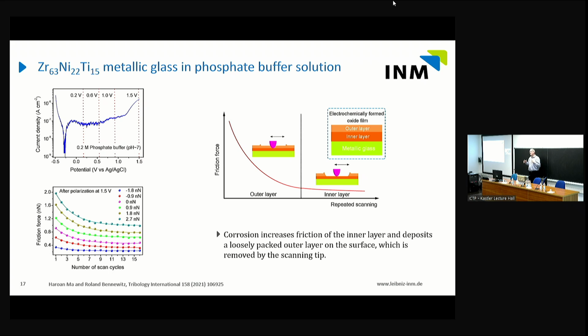And so what we do here is we first oxidize, stop, and then do friction force microscopy, and you can see that the friction is going down as a function of cycle number, how often we scan back and forth, and as a function of load, we see that the friction goes up with higher oxidation potentials, and our idea is sketched on the upper right. So we have the bulk metallic glass, then we have an oxidized layer where the metallic glass itself is oxidized, but then we also have oxy-hydroxy products which are released, diffused to the surface, and loosely attached to the surface. We call this the outer layer.